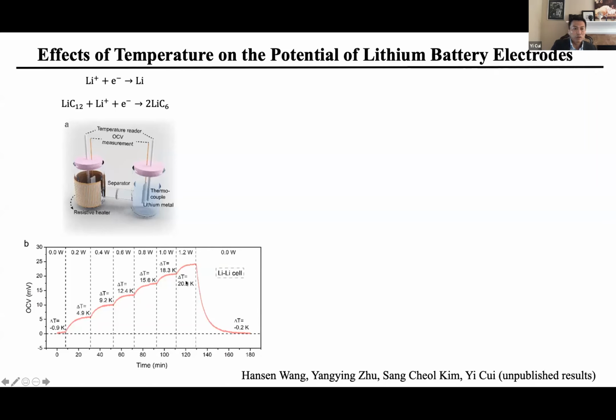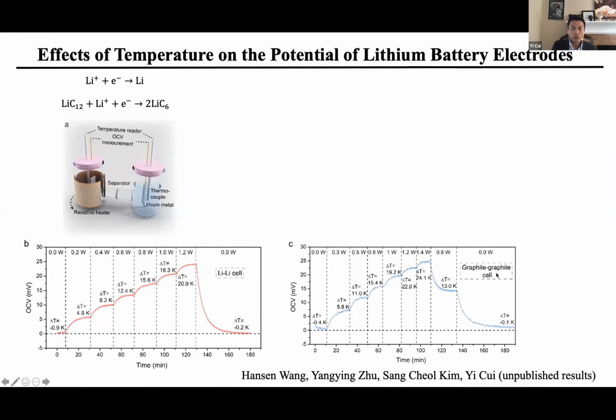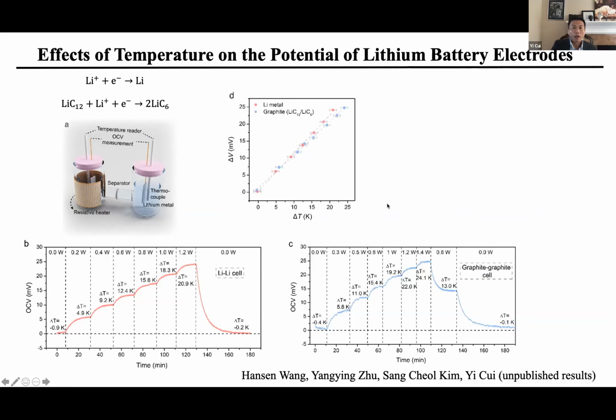And this is for lithium metal. And then we can measure the graphite as well. And you plot this. This is the voltage change versus temperature. This indeed is giving us a linear temperature coefficient on the order of about 1 millivolt per Kelvin, also per degree Celsius. So this is actually a very high temperature coefficient right there. What does it mean? Once you increase the temperature, the voltage goes up, right?